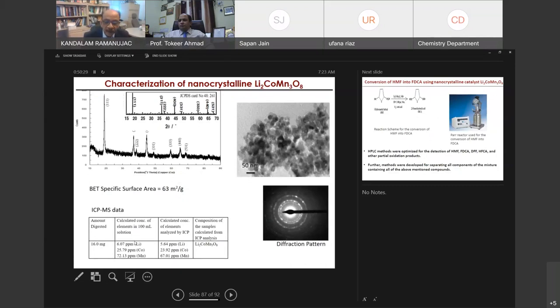We also have done ICP analysis, mass spec, to make sure that the lithium, cobalt, and manganese ratios, whatever the target ratio and whatever we used in the initial mixtures, are not lost. So they're all pretty much conserved here. So this is the composition finally, Li2CoMn3O8. To our knowledge, this is the first time that a double spinel is used for the oxidation of HMF to